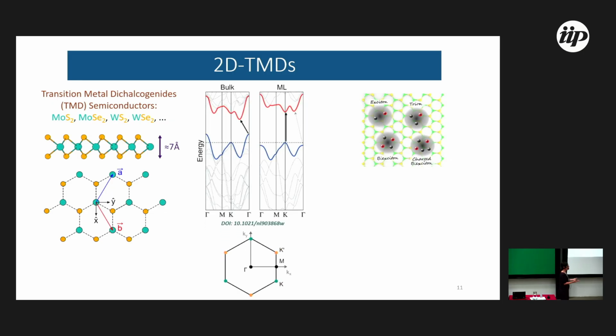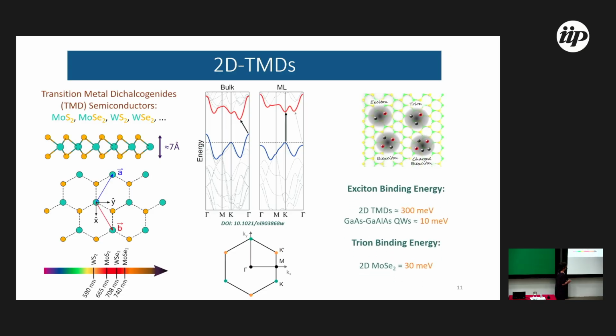TMDs have hexagonal crystal structures. When you have bulk, it's an indirect gap semiconductor material, so it's not nice. The PL, photoluminescence, is very low. On the other hand, if you have a monolayer, it's a direct gap semiconductor material, so there is strong emission of light. And so you can have a very good system to measure photoluminescence.